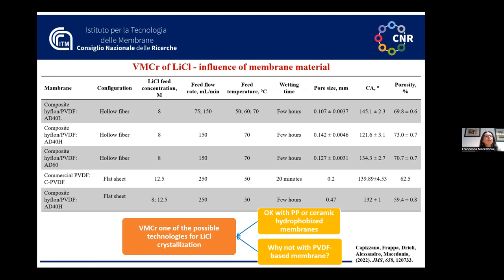Then we tried to see if PVDF can also be used for the crystallization of lithium chloride, and tested various membranes: only PVDF, the commercial one, or some composite membranes, PVDF Hyflon. In all five tested membranes, we could not achieve the crystallization of lithium chloride due to irreversible wetting. Wetting can occur in membrane distillation and membrane crystallization, and usually when we observe wetting, we wash the membrane, dry the membrane, and the process can be restarted. But in the case of the test with lithium chloride and the PVDF membrane, this procedure was unsuccessful.